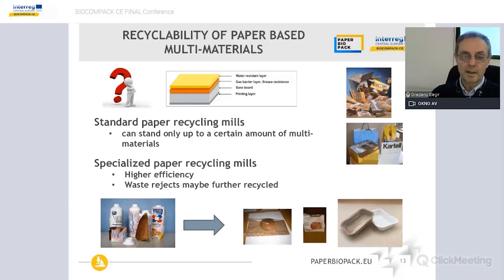What can we say about the recyclability of this multi-material? Well, first of all, I have to point out that technically all these products are recyclable. It's not only a matter of technological constraint. The real problem is that the standard paper recycling mills can stand only a certain amount of multi-material. The reason is that some of them disintegrate slowly, and this is a technological problem, but the major problem is probably an economical factor, because they generate a higher amount of waste that the standard paper recycling mill cannot handle.